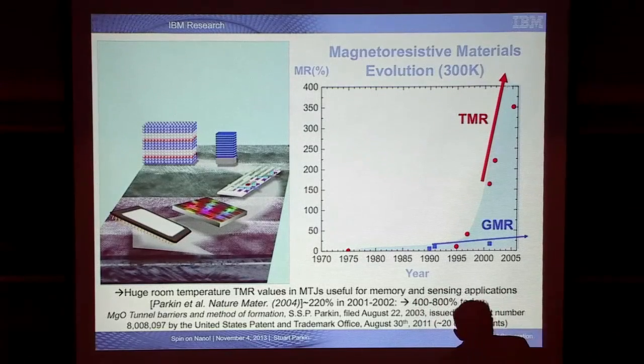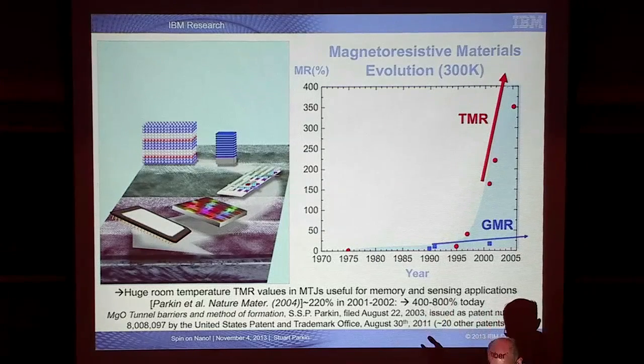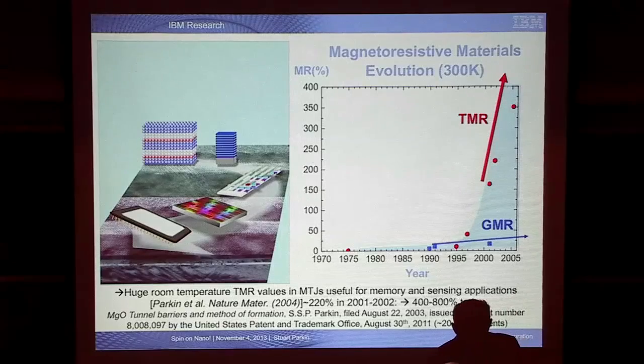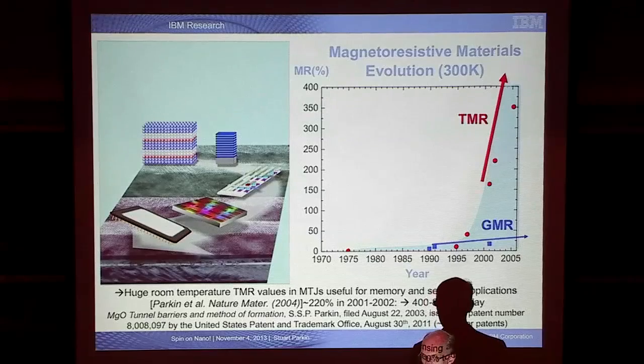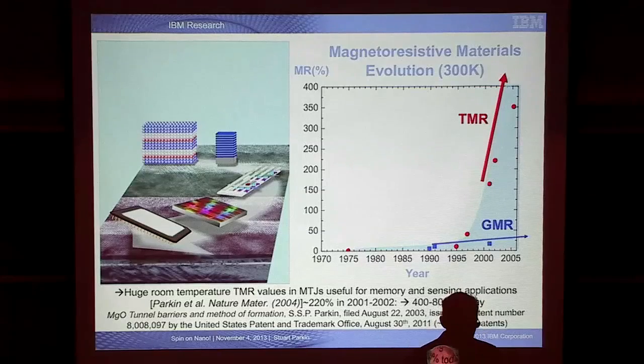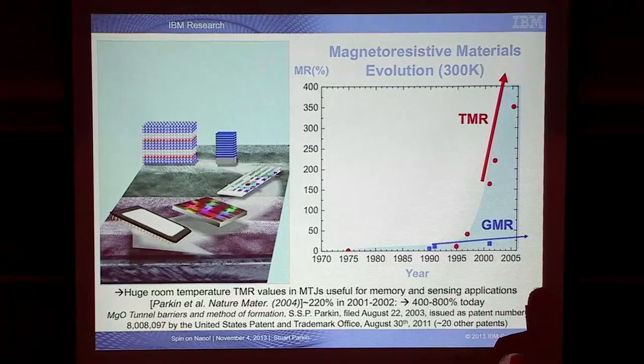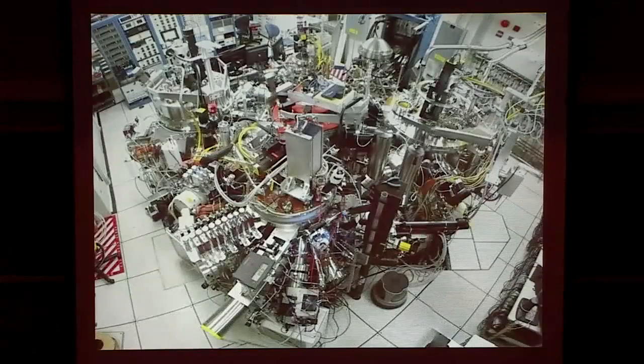And so what does that mean? It means, it turns out, since this discovery, we made it in 2001 and we patented it shortly afterwards, it means that since 2007, magnetic disk drives, the information is detected not using this metallic spin valve, but using this magnetic tunneling junction device. Although if you looked at the device, it would look very similar from a structural perspective and a spin engineering perspective. So now, that was the story about magnetic tunneling.